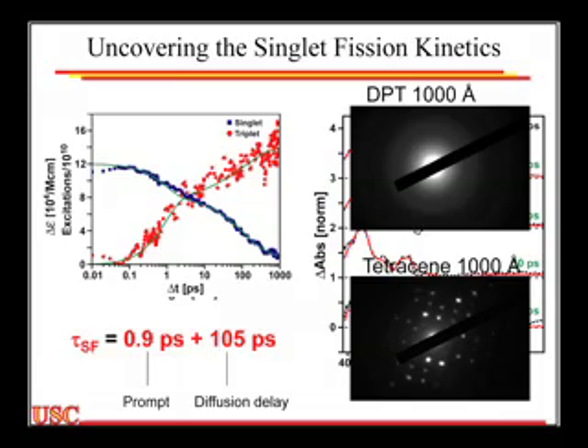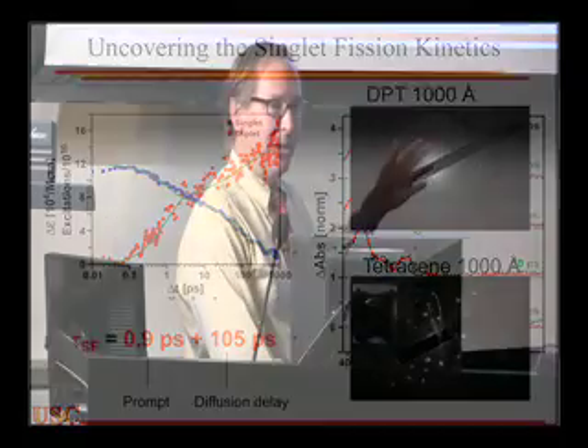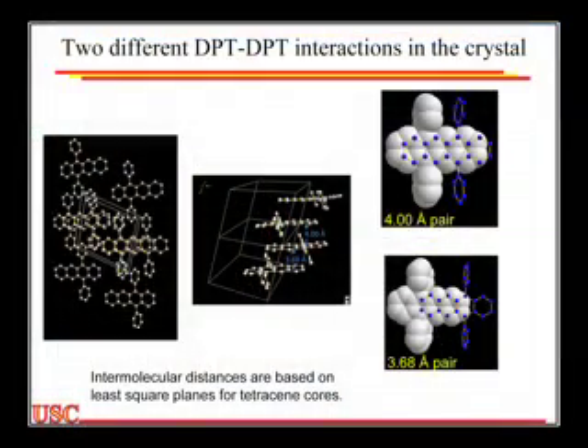We have some idea what those sites might be, because we can get crystals, not in our thin film, but I can grow crystals intentionally. This is the crystal structure of DPT. Sorry, this doesn't show up very well either. But it doesn't form a herringbone, it forms infinite stacks, and the stacks alternate spacing of 3.5 angstroms and 4 angstroms. The 3.68 angstrom ones are shown here. It's a slip stack, so they're not cofacial, they're actually slipped relative to each other. The cofacial derivative is much wider, about 4 angstroms.